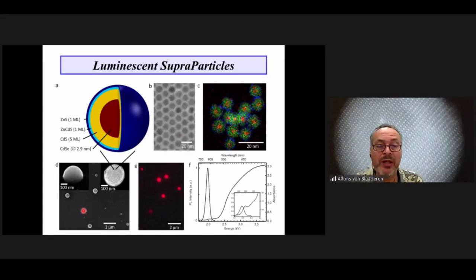So we're going to build up from core-shell quantum dots. They have a cadmium selenide core in which an electron-hole pair can be generated, and it's a strong function of the size of the semiconductor core. But then we make a core-shell structure in such a way that when the particles are very closely connected, their quantum mechanical wave functions don't overlap.